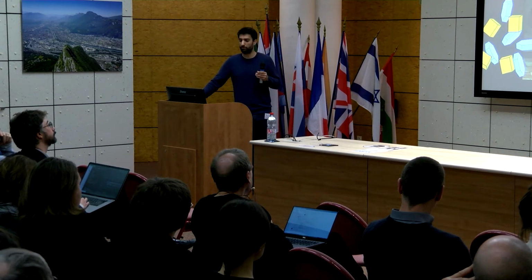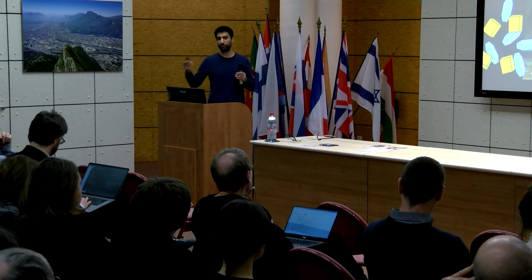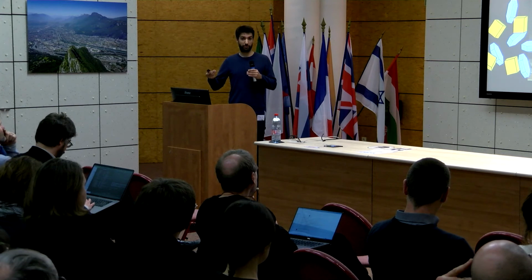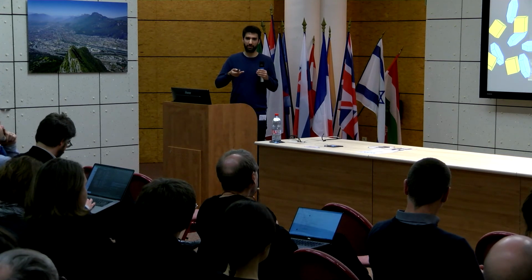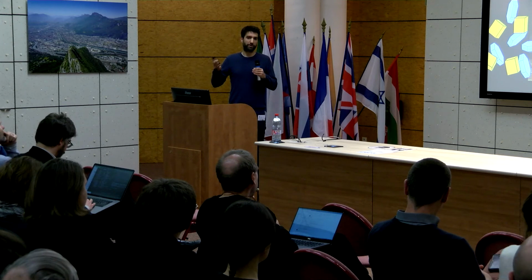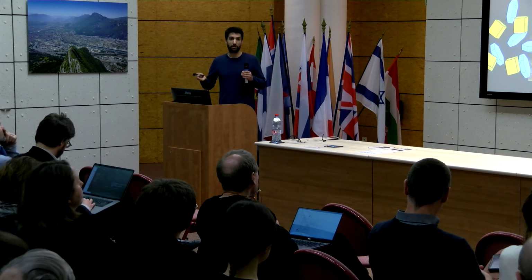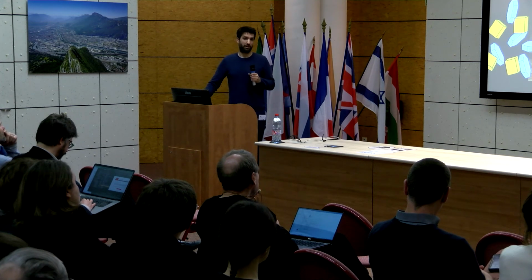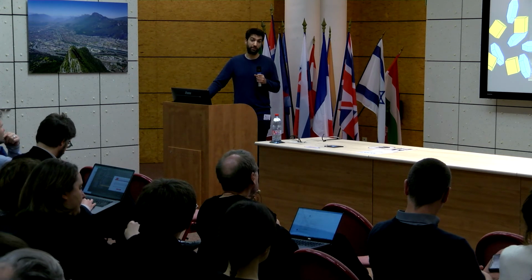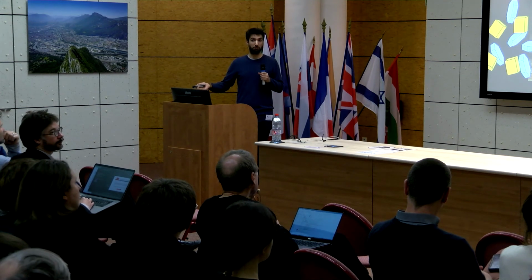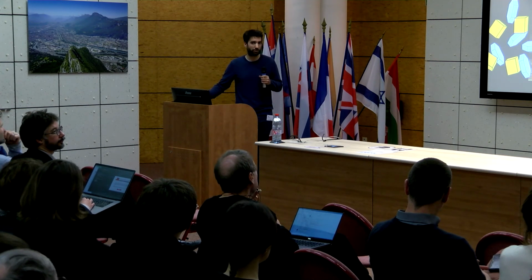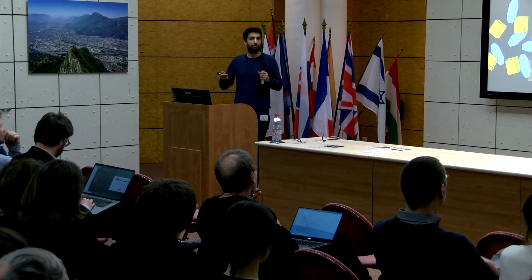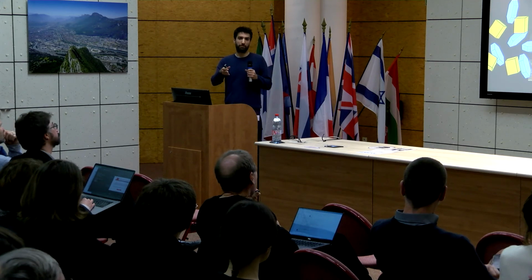But I should say also that we have performed some other beam time, for example, at Diamond and I-18, where we have worked on a lot of model samples where it seems to fit that plumbonacrite crystallizes when litharge is present. But then, of course, is it only something due to the oil? We still have a lot of work to do on this specific phase, and I know that your team detected plumbonacrite in obviously non-impasto layers because they are coming from other paintings, other painters. So this is perhaps not the only chemical pathway to plumbonacrite.